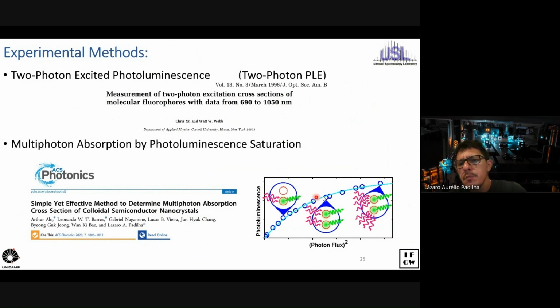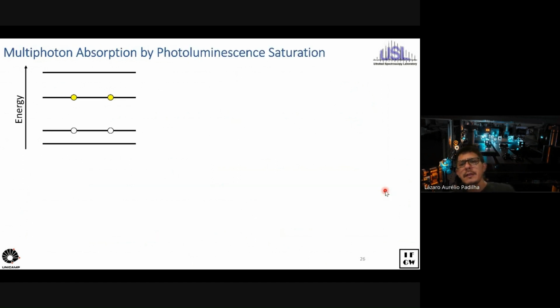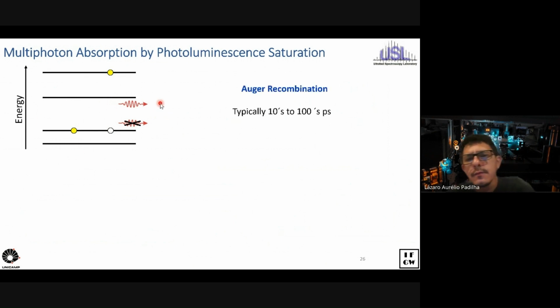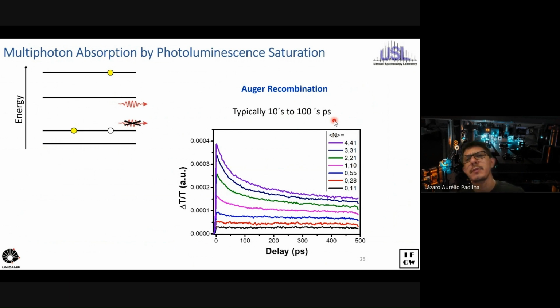And this technique basically takes into account the saturation of the emission due to Auger recombination. What I mean by that is that when you get into a quantum-confined material and you excite more than one exciton, instead of emitting two photons, the second exciton recombines by transferring its energy to one of the carriers of the other exciton. This process is called Auger recombination, and it makes two excitons emit a single photon. Auger recombination is typically 10 to 100 picoseconds, while the emission or PL lifetime is in the tens of nanoseconds, which makes